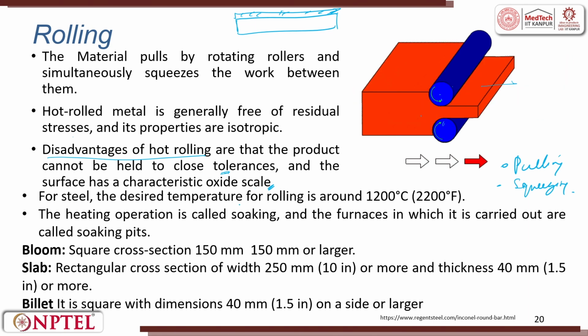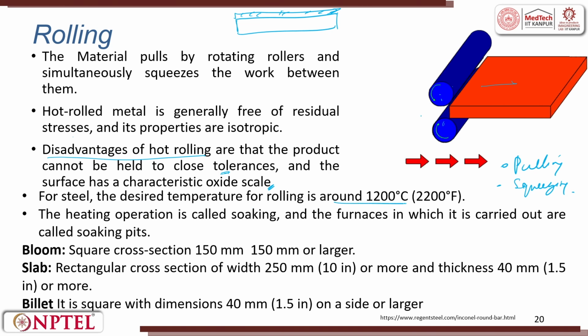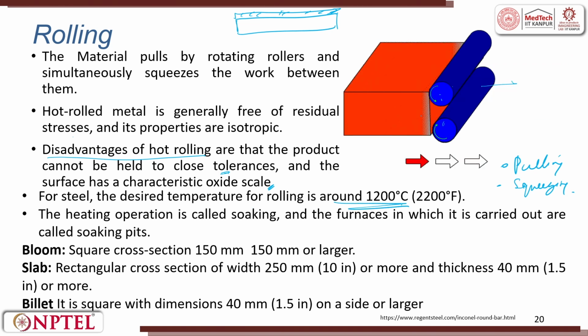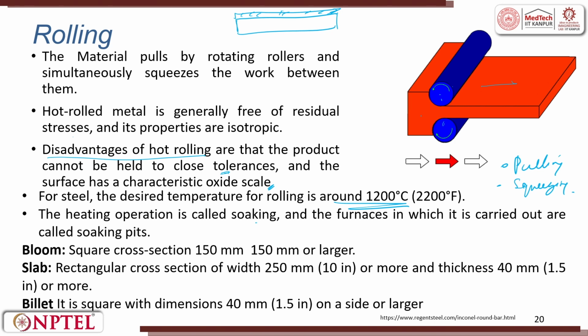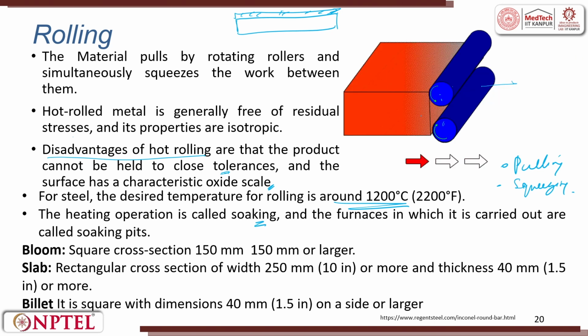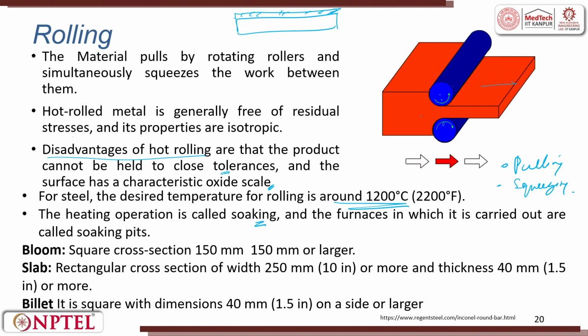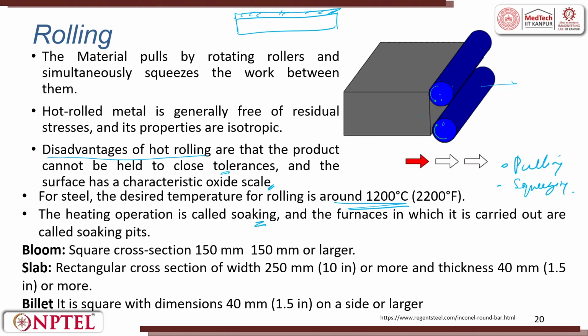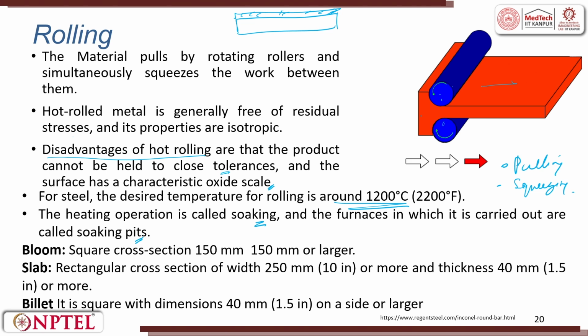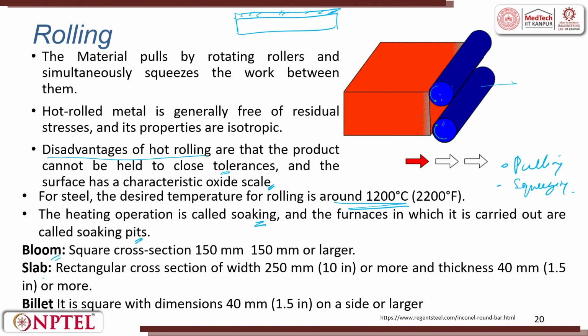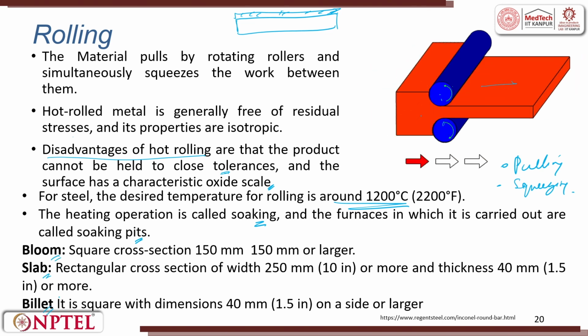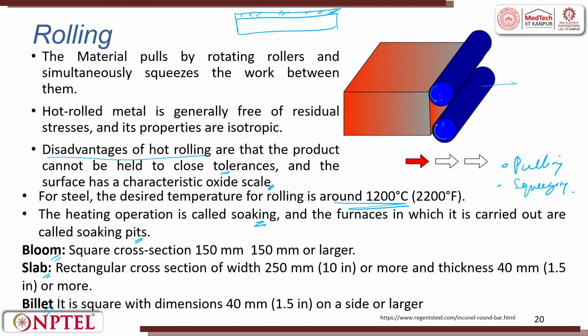For steels, the desired temperature for rolling is around 1200 degrees Celsius. The heating operation is called soaking. We saw this in the previous chapter when we looked into heat treatment, soaking, and the furnace in which it is carried out is called a soaking pit. Blooms, slabs and billets are different types of workpieces.